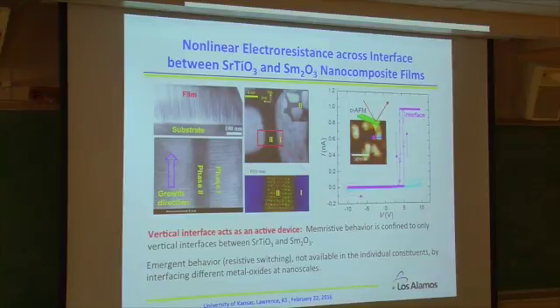Okay? Right across the interface, you form this kind of conducting channel. You think about this, you can really use this more like a resistive switching device. Of course, when you try to do this, picking up this interface is tough, but at least you can still pattern the electrode. You can do this kind of method.